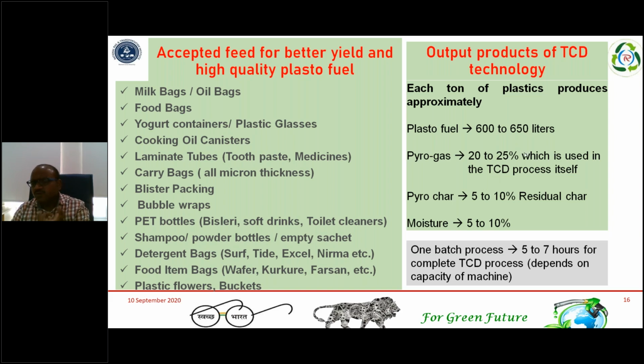Means if I put 1 kg of raw material, I will get 0.6, 60% of the oil, 20 to 25% of the gas, and the remaining would be the char, the solid residue, and some amount of moisture is present in the output products. One batch process is about 5 to 7 hours.